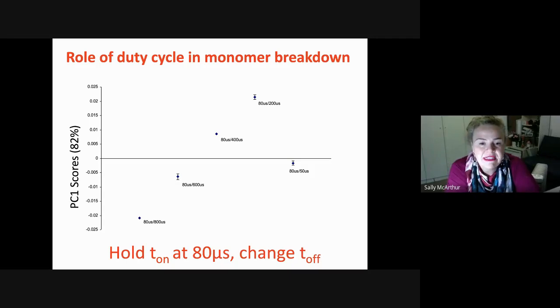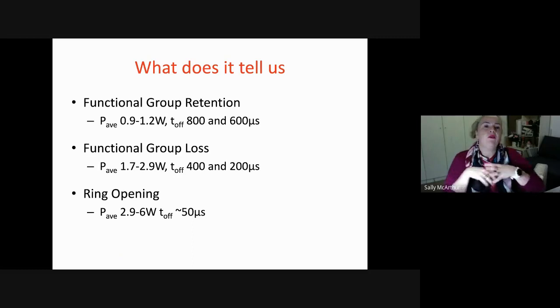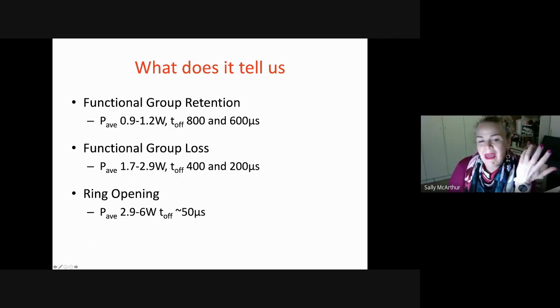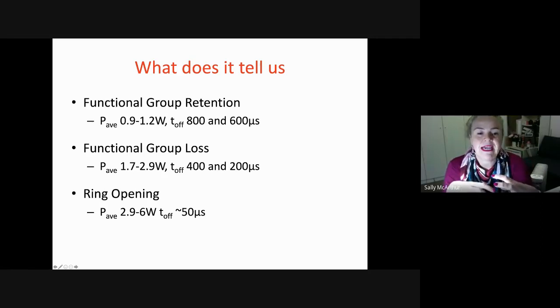That's obviously coming down to very slight changes in the total power in the system. So when we look at that more generally, we can see that if we start with what causes ring opening, if the average power in the system is higher than about 3 watts, and that correlates to an off time of about 50 microseconds, we see full ring opening. So our TOF-SIMS data shows us the specifics of the chemistry. We get functional group loss when we're between about 1.7 and 3 watts. So that's off cycles of around 200 to 400 microseconds. But we see functional group retention when we've got 80 on and either 600 or 800 off. So that's somewhere between 0.9 and 1.2 watts.